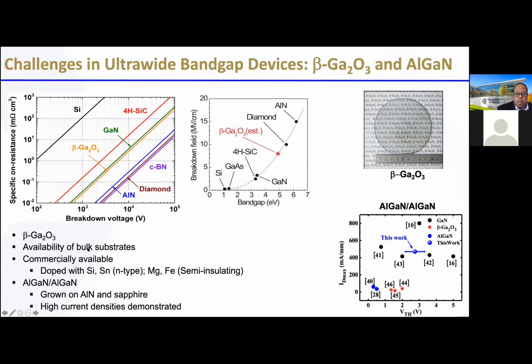You can buy these commercially, doped with various dopants, even semi-insulating. And so there's this nice push in terms of the thought that the price is going to come down, but there's still a lot of work to be done here. I'll show you the challenges next. And then AlGaN. You can grow these on aluminum nitride and sapphire, which are, again, readily available. And again, you look at current densities. The current densities of AlGaN transistors actually can be higher than that of gallium nitride even today.